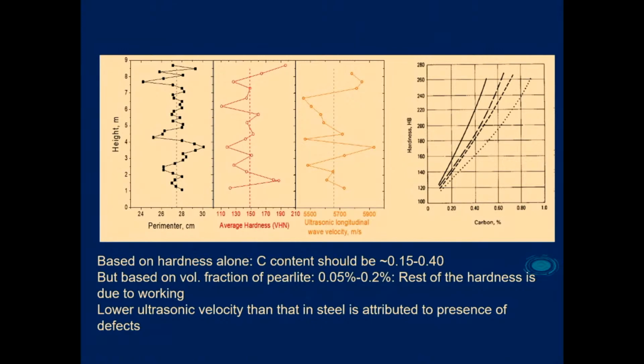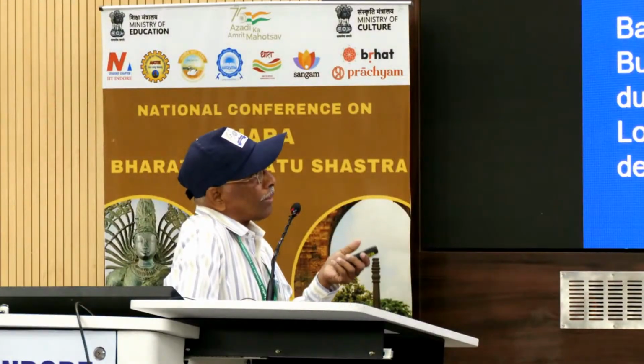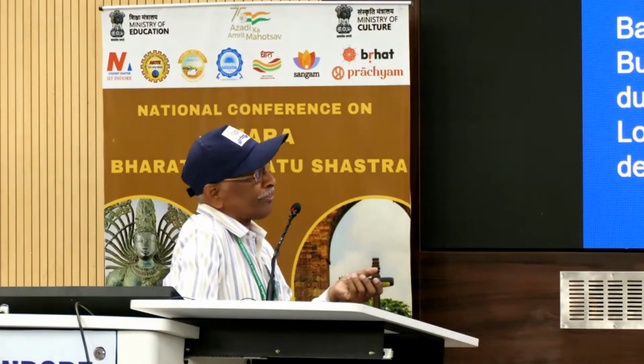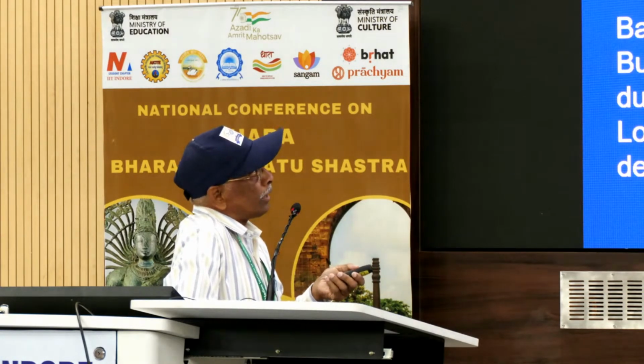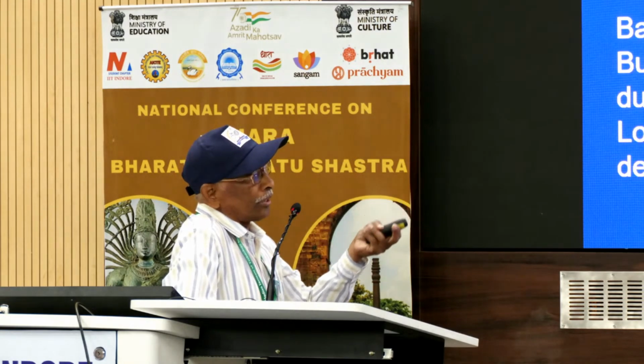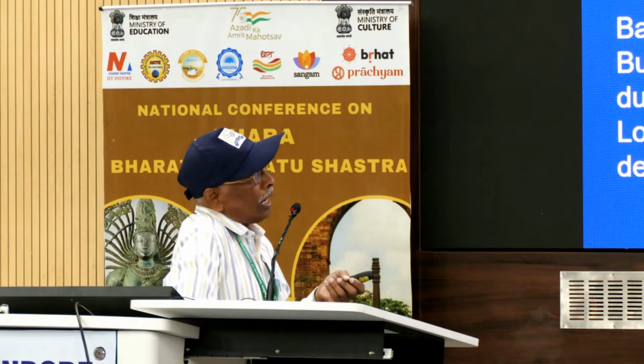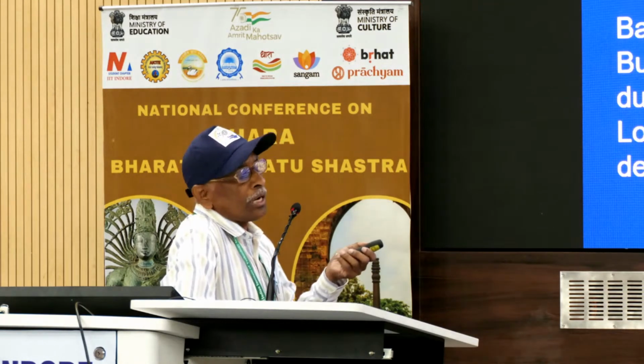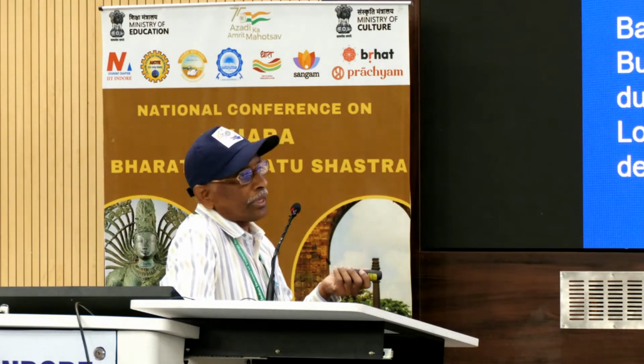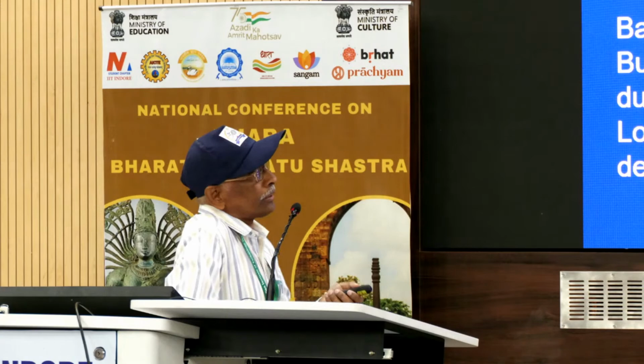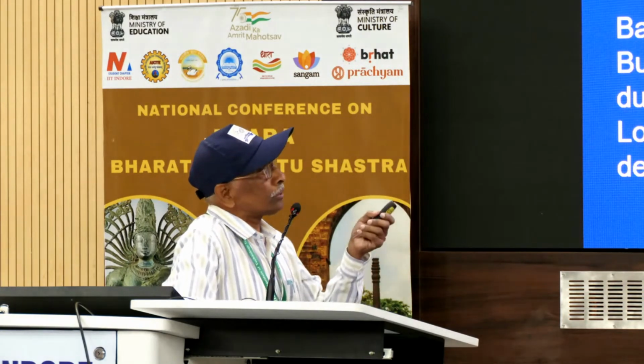And if you see the hardness variation and the composition of the carbon which we have taken based on the ferrite pearlite percentages, and the expected hardness taking into account certain heat treatment conditions, the hardness of the pillar is more than you can account for from the carbon content inferred from the ferrite pearlite compositions. So what we believe is that it is in the worked condition, so that's why the hardness is more than what is expected in an annealed ferrite pearlite condition. So that is another information we could obtain.